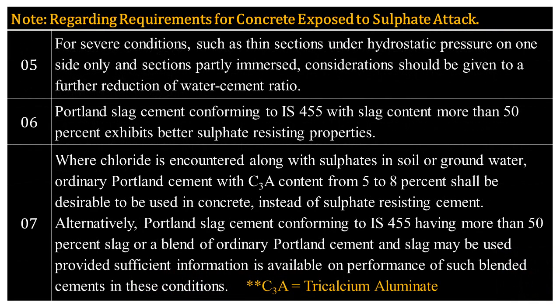This slide continues the discussion of notes below Table 4. Note 5: For severe conditions, such as thin sections under hydrostatic pressure on one side only and sections partly immersed, consideration should be given to a further reduction of water-cement ratio. Note 6: Portland slag cement conforming to IS 455 with slag content more than 50% exhibits better sulfate-resisting properties.